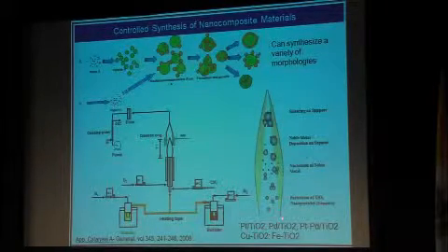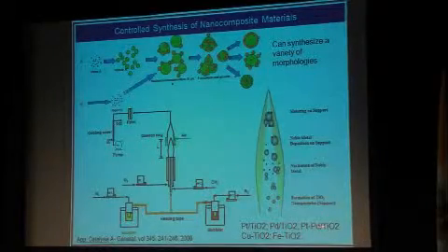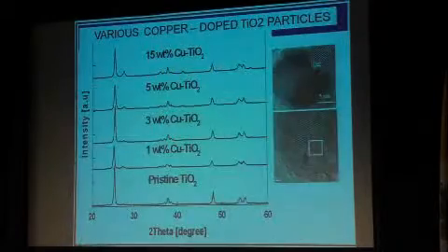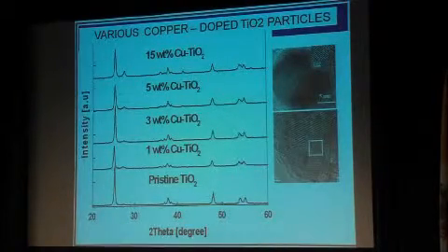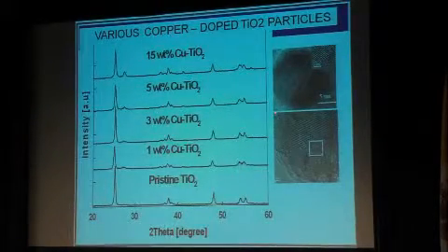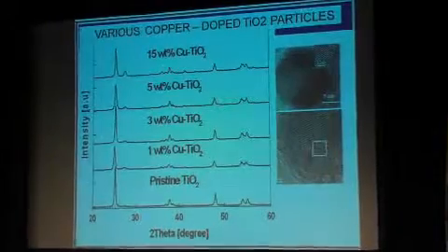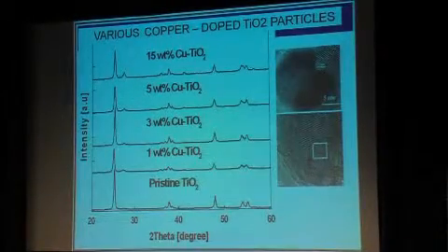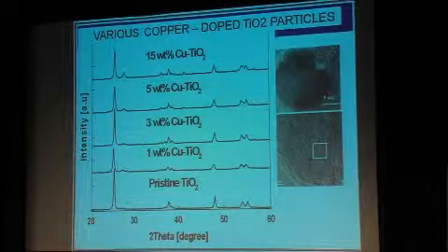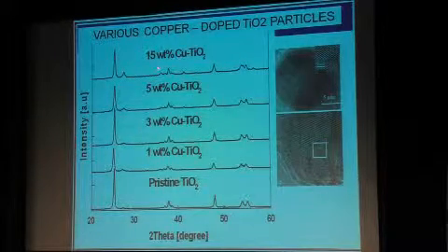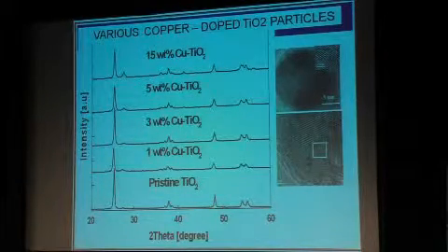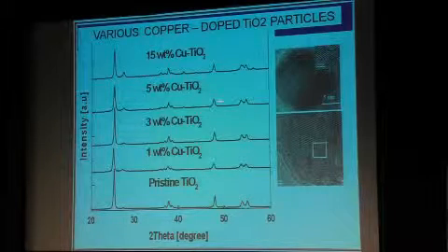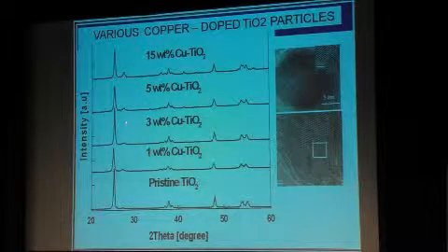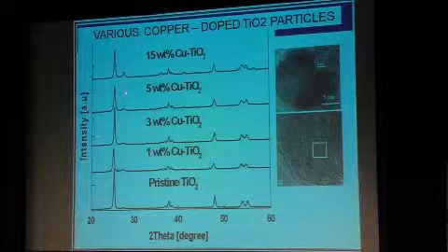Again, processing conditions very readily allow us to prepare these things. And again, we've made platinum-doped TiO2, palladium TiO2, platinum palladium TiO2. So you can play with all these things and come up with a whole mix of materials. Here are some pictures of copper-doped TiO2. Now, if you look very precisely, this copper is in an oxidized state. Here, of course, it's quite a bit of copper. The other interesting thing, you still don't see the crystal phase of copper oxide. So it's an amorphous state, but it begins to promote formation of the rutile phase.